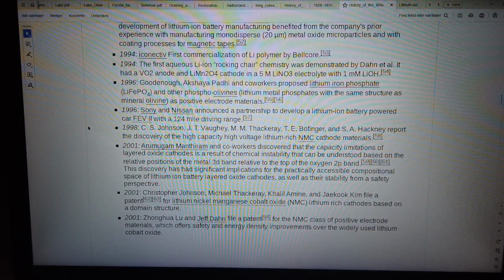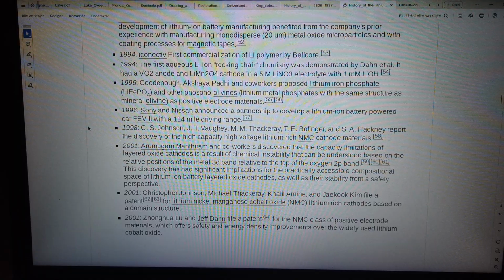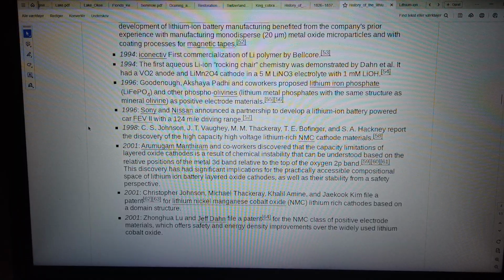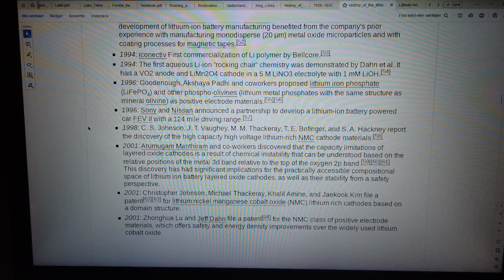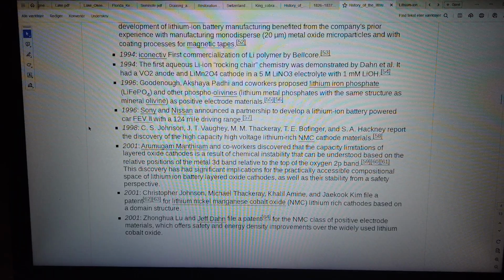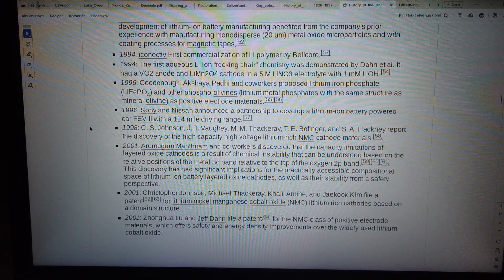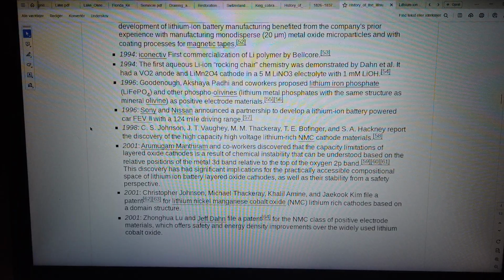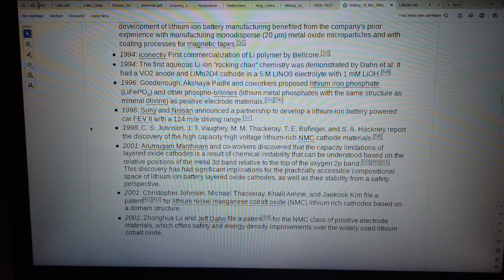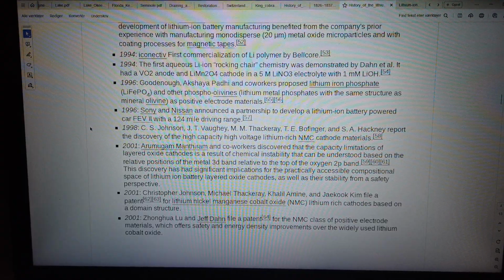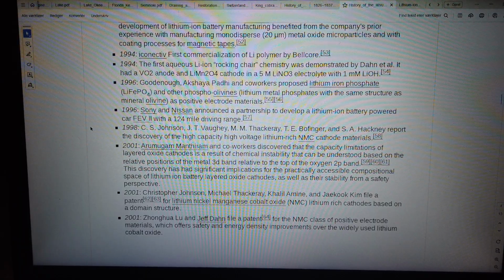2001, Arumugam Manthiram and co-workers discovered that the capacity limitations of layered oxide cathodes is a result of chemical instability that can be understood based on the relative positions of the metal 3d band relative to the top of the oxygen 2p band. 59, 60, 61. This discovery has had significant implications for the practically accessible compositional space of lithium-ion battery layered oxide cathodes, as well as their stability from a safety perspective.